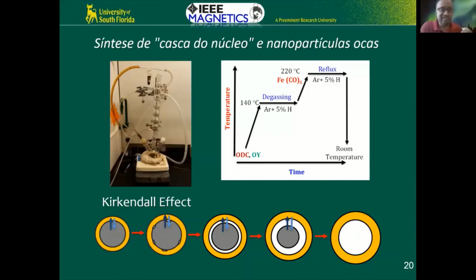So if your first intention was to show lovely hollow nanoparticles, this is the way to go. Make core shell particles and let the Kirkendall effect play the role to convert them into hollow nanoparticles. Unfortunately, this is not good for our application because we want these particles to be stable over time, because we want them to be effective for hyperthermia, to have a large SAR.